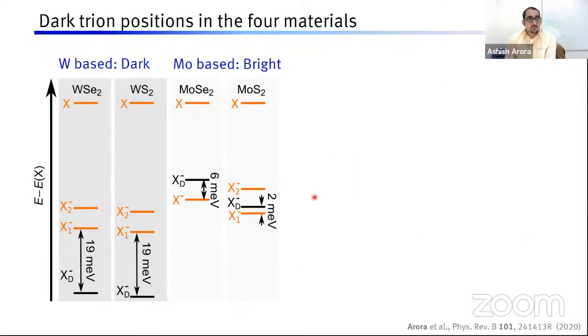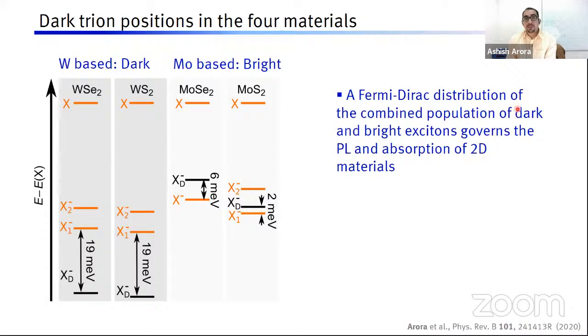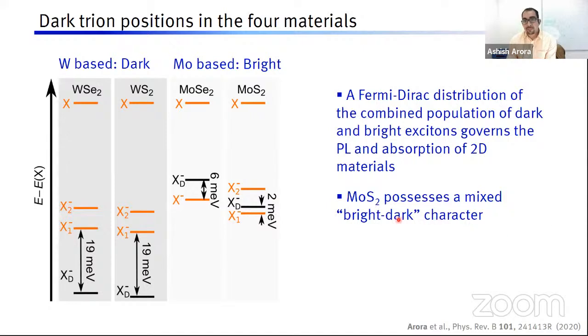Therefore, in conclusion, we find that a Fermi-Dirac distribution of the combined population of dark and bright excitons governs the photoluminescence and absorption of 2D materials. Tungsten-based materials are dark by 19 meV. Molybdenum-based materials are bright, or MoS2 is actually a mixed state.